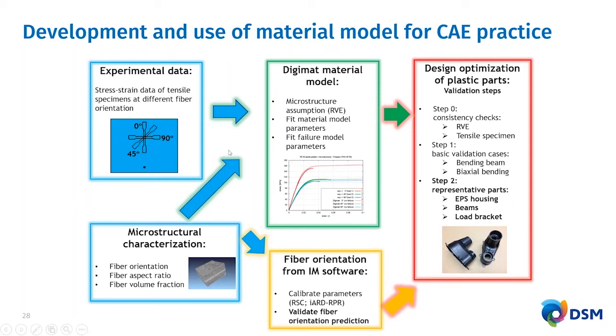So here on the left, we begin with experimental data measurements utilizing a large plaque, and we cut these specimens out of the plaque at different degrees of orientation, in the flow direction as well as the cross flow, and then there will typically be one at 45 degrees. And this dot here represents the gate location. So these measurements are then fed into our Digimat software to create these Digimat models that ultimately feed into our FEA simulation. There's also some other microstructural characterization, including fiber orientation, the aspect ratio, and the volume fraction, that's used as a verification of the Digimat model.